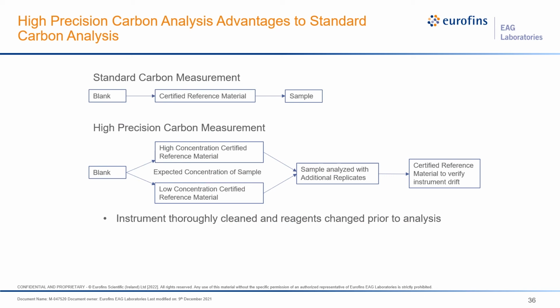To achieve high precision, a different approach is used. In standard carbon measurement method, we analyze blanks, then certified reference material, and then sample. However, for high precision measurement, we adopt a stricter statistical approach where after analyzing blanks, we do analysis of two reference materials. One reference material has higher carbon concentration than the expected concentration in sample. The other reference material has lower concentration than the expected carbon concentration in sample.